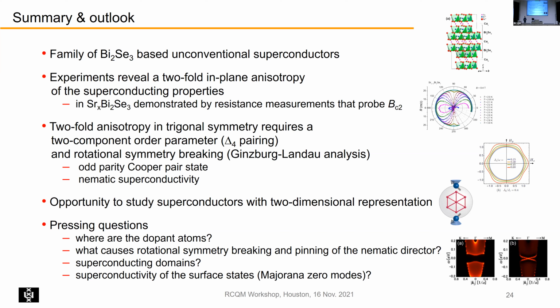Yeah, I think we would very much like to do such experiments, but the problem is with the purity of these materials. The residual resistance ratio is not very good for these materials. And superconducting volume fractions are always somewhat limited. So any thermal conductivity experiment you want to do is very difficult. Penetration depth measurements have been done, but it's very difficult to interpret.